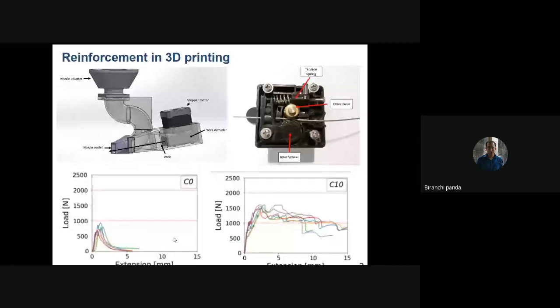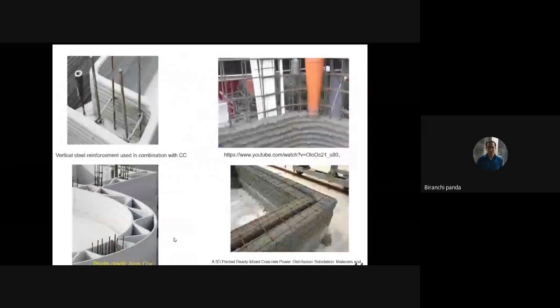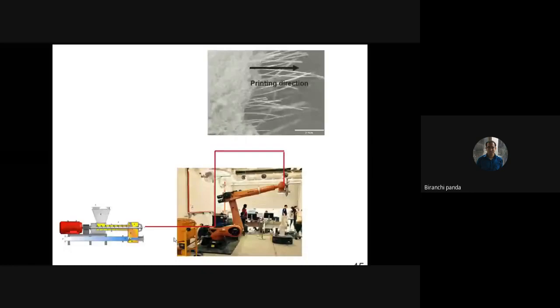But in the literature, there are many possible ways. After printing, they install the rebars, or they simply print over the rebars. There are different approaches by which reinforcement has been added to concrete structures. We have also printed some fiber reinforced concrete. It's very easy, but we have to optimize the mix design again for this robotic system, so that we can print fiber reinforced concrete just by adding the fibers. But since this is an extrusion-based process, we found that the fibers align in the printing direction. Once you print the filament, if you break it and look under the microscope, you can see that because of the high extrusion pressure, these fibers are always in the printing direction.